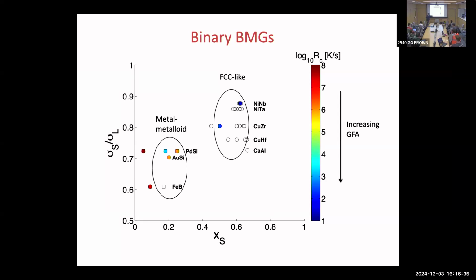And so one thing that is going to be important is the size ratio. I think everybody knows that if the particles are the same size in 2 dimensions, 3 dimensions, 4 dimensions, whatever, they have a greater tendency to crystallize. So one thing that can frustrate crystallization is that the sizes are different. In this particular way I'm plotting it, it's the diameter of the small atom divided by the diameter of the large atom. And so it's by definition less than 1. And so if this number is close to 1, then it's not a very good glass former. Then the other thing that may be important is what's the fraction? So you have 1 is small and 1 is large, but how many of the smalls do you have? How many of the large do you have? And probably you could guess that you don't want an overabundance of one over the other, because then they can sort of segregate.